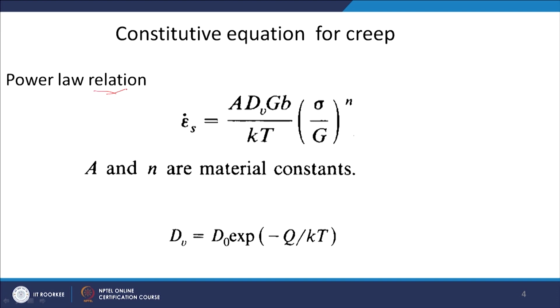a power law relation. So epsilon dot, okay. Now you can see that when we talk about creep, we don't relate stress with strain rate, temperature and so on. We relate strain rate with the stress, okay, because in this our control variable is the stress, the load which we are applying, the constant load or constant stress which we are applying on the material, and looking at the strain as a function of time, okay.